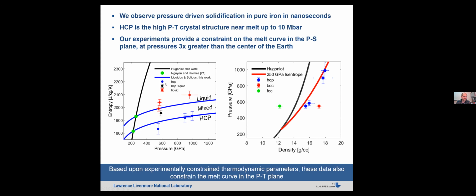And then what I'll show here is our final plot of the data in the pressure entropy plane. So this is entropy and pressure from 150 up to 1250 GPa. Again, the black line is the Hugoniot. The green points represent the pressure for incipient melting and pressure for complete melting. And then our data points where we measure liquid are shown in red, the mixed phase is in black, and HCP is shown in blue.